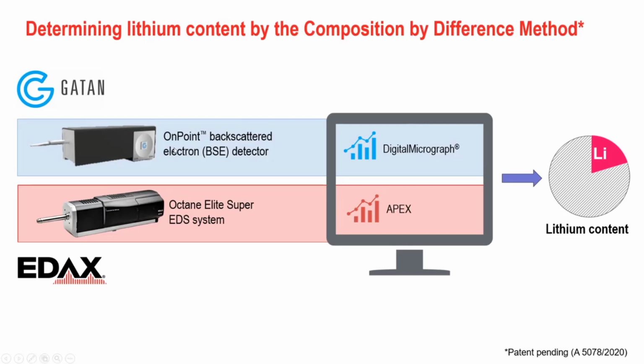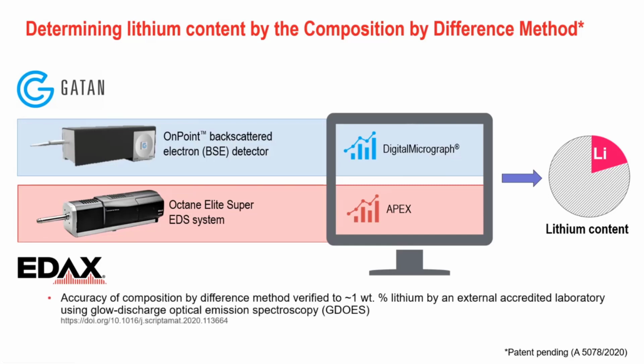What we can do there is we know the elements we see. We can calculate the backscatter coefficient we expect. With a calibrated backscatter image on the OnPoint detector, we can see what the difference is from what we expect based on the chemistry. And that difference can be assigned, in this case, to lithium. And then we can quantify the lithium content. This has been confirmed with another tool, so we're pretty sure that we get this right.